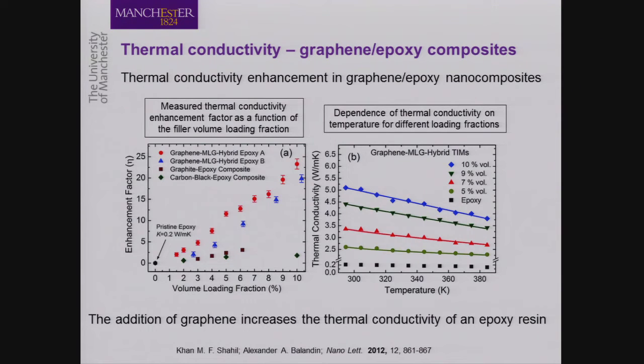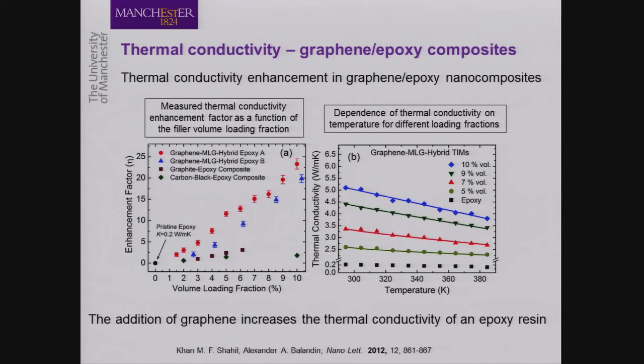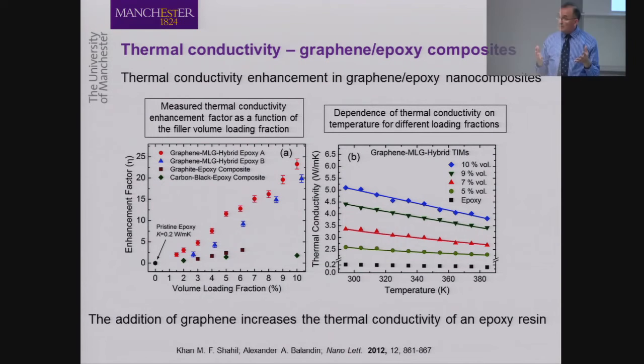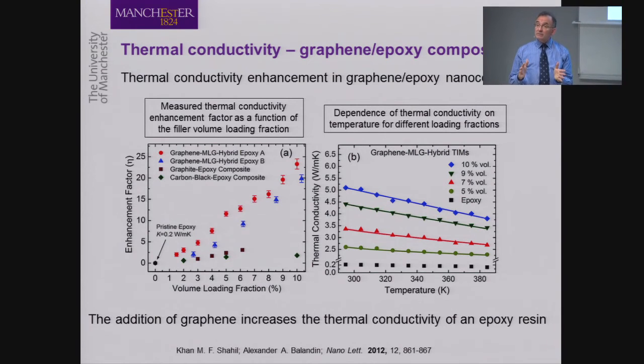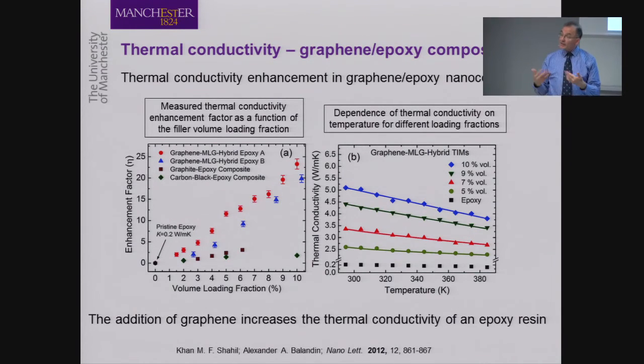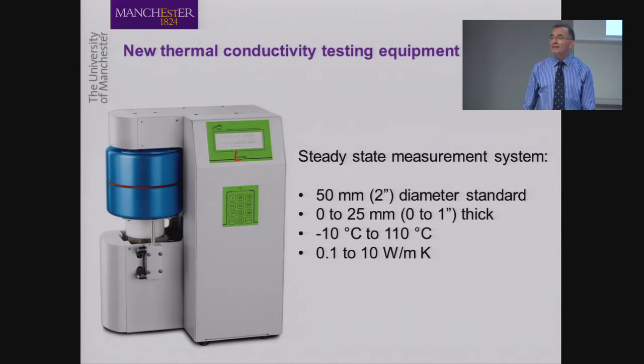Now, if we look at other properties outside mechanical response and mechanical behavior, if we look at thermal conductivity, we're going to see that we can increase the thermal conductivity dramatically. And that is a beneficial thing, especially when in the aircraft industry, we would like to do something about heat management and how we can dissipate heat quickly in a non-metallic structure. So there we can see straight away a huge benefit by modifying the thermal properties of our component. And you need appropriate equipment to make those measurements for the thermal conductivity.